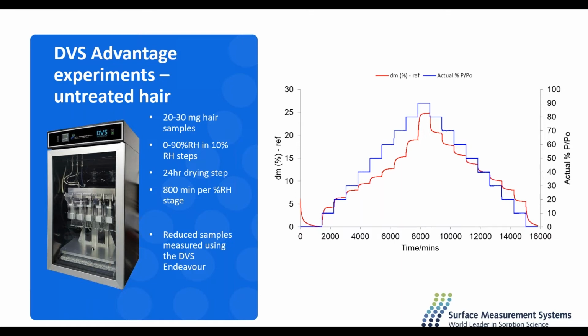However, one cause of hysteresis in water sorption isotherms to hair, which has been proposed by some researchers, is that the hair samples haven't reached full equilibration. So to really make sure that we weren't missing out any kinetic data, we stepped 800-minute steps for each stage. And this led to an 11-day experiment, so quite a long experiment there. But as we can see in red for the change in mass with each humidity step change in blue, they have all reached a really nice equilibrium before moving on.